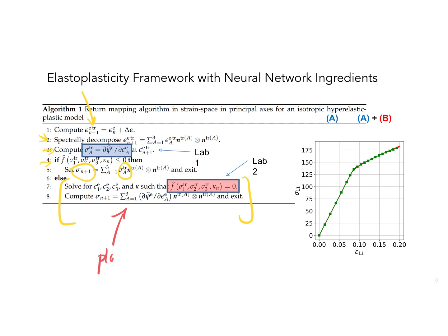This is the part that we need to talk about in detail, and then maybe we need to solve it with Newton-Raphson. I need to find out what happened to the plasticity. What I mean is that I need to find the stress, because of the stress update algorithm. Or equivalently, I can say that I need to find out what the elastic strain is, which is the same way as saying that I want to find the stress. Do you see why?